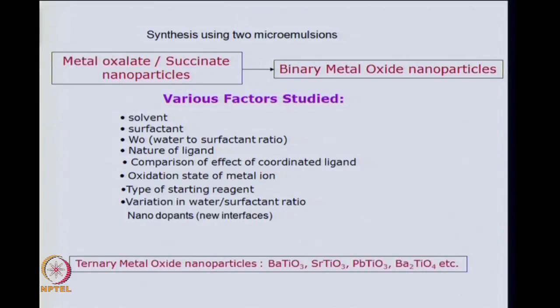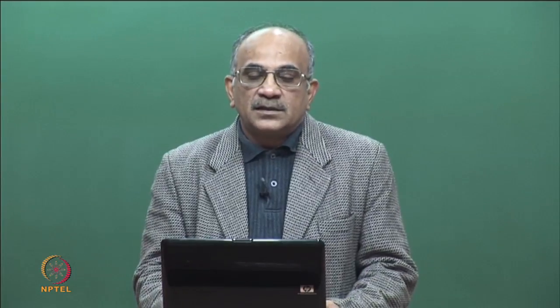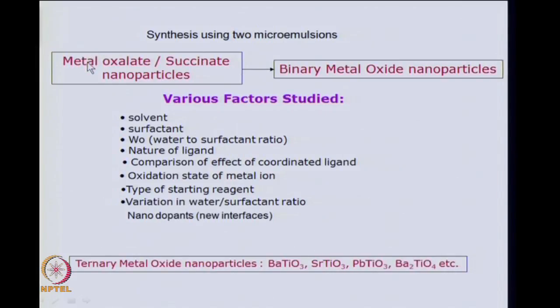Now, typically how do you synthesize nanostructured materials? So, we will study how we synthesize using two microemulsions, by which we get metal oxalates or metal carboxylates and then generate binary metal oxide nanoparticles. In our earlier lecture, we discussed that whenever we have to make nanomaterials using microemulsions, we start with 2 or 3 or 4 microemulsions, depending on whether we want a binary oxide or binary chloride or ternary material or quaternary material. Depending on that, the number of microemulsions that you take increases. So, in this case, since we want to synthesize binary metal oxide, that means one metal and one oxide, oxygen species, you need 2 microemulsions to start with.